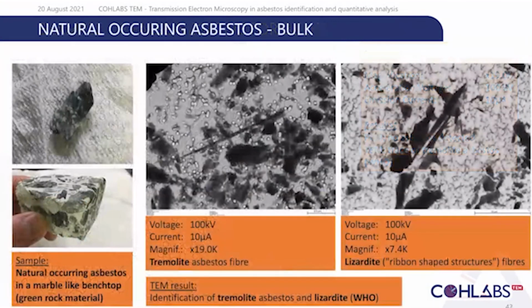An example of naturally occurring asbestos. This sample was a marble-like benchtop from a green material. As you can see, there are different fibers here. On one side, we found tremolite asbestos fibers, and on the other side, we found another material, which is not asbestos. It's called lizardite. Both materials were under the WHO characterization for fibers. So we were able to differentiate which one was indeed asbestos and which one was not asbestos.